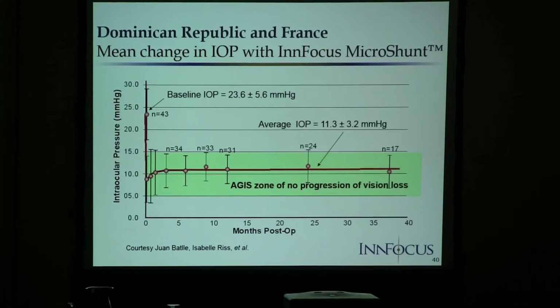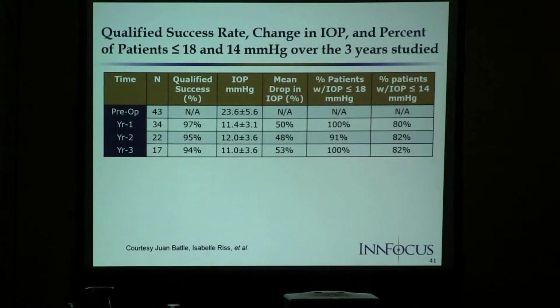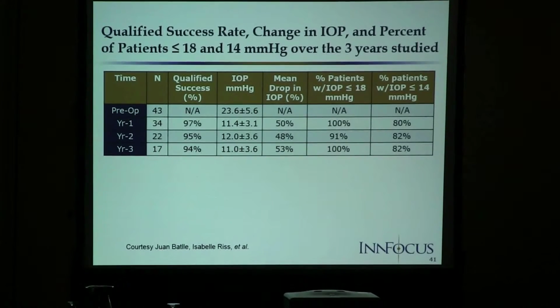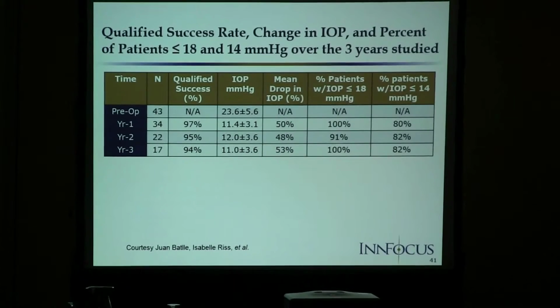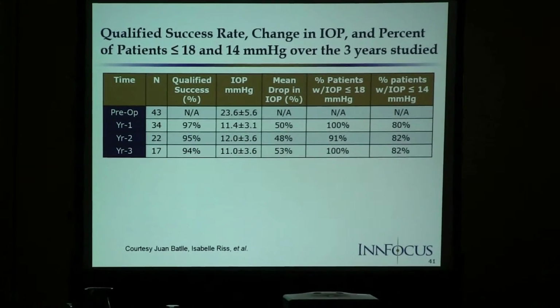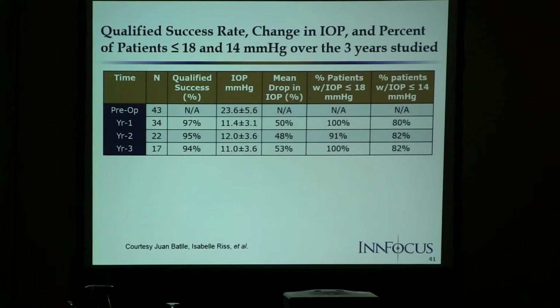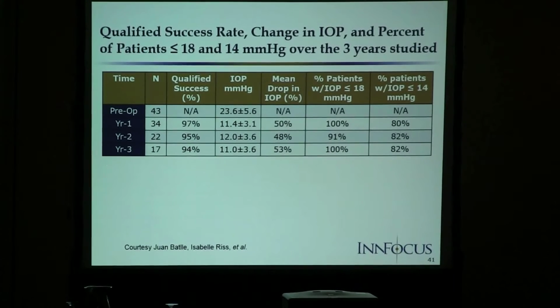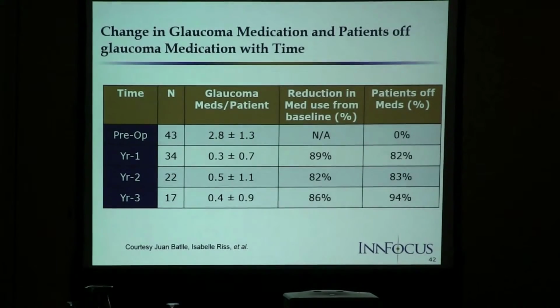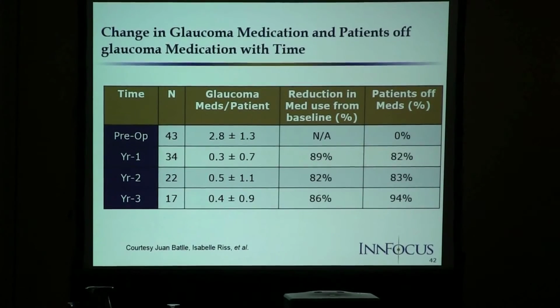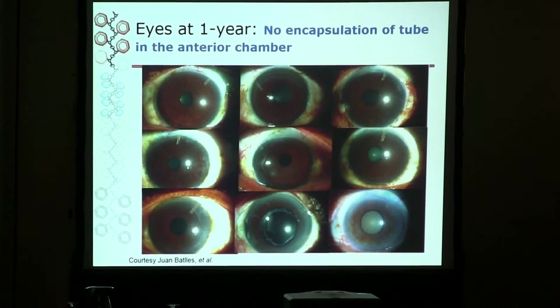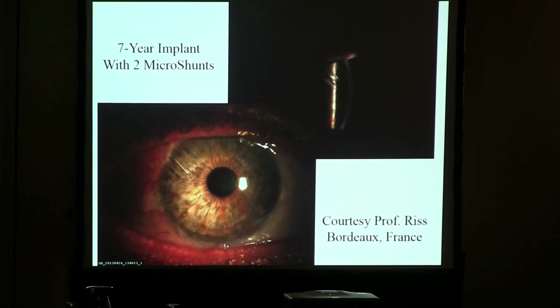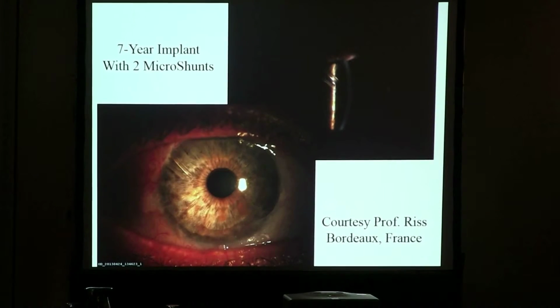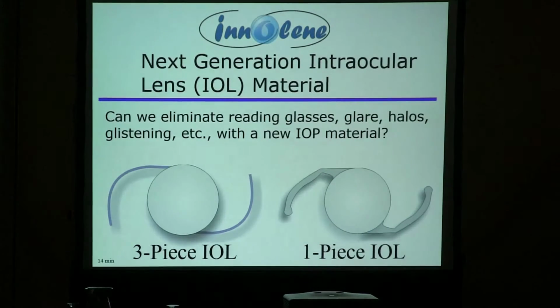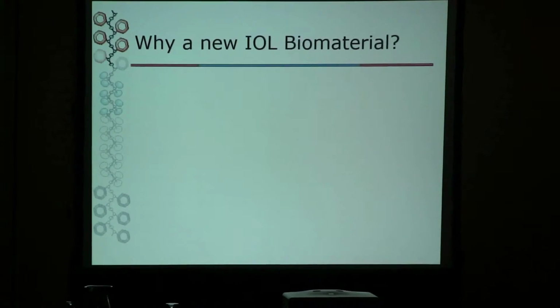And we're waiting for more of our N value to increase with time. Just looking at the data at year 3, we have a 94% qualified success rate. I talked about the pressure being around 11. And we also have a reduction in meds to about half. And this is just some pictures showing that it's really benign. And here's a patient at 5 years with 2 of them in, because if one fails, you can put another one in. So we also make intraocular lens out of that.